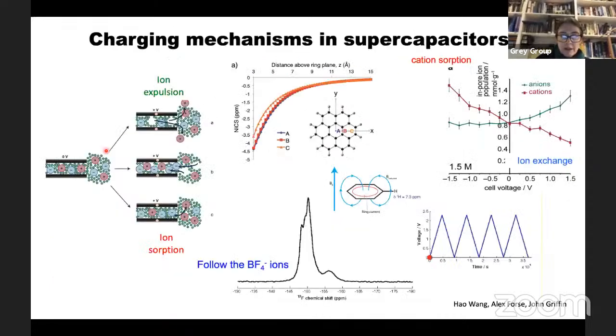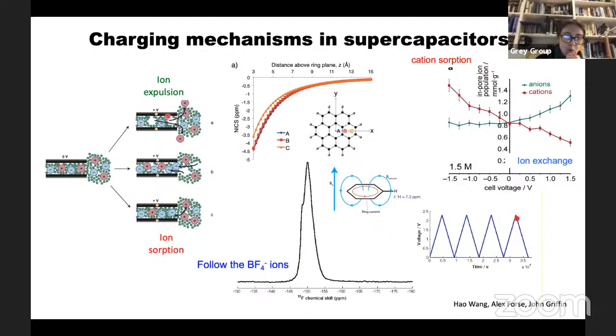And surprisingly enough, when we started in this field, people hadn't worked out how these compounds actually worked. These activated carbons consist of sheets of carbon. They're very graphitic. And if you do a thought experiment and you say to yourself, at 0 volts, I'm going to charge it positively. How do I store charge? Now, I said it was in a double layer, but it's a bit more complicated, it's really to do with how ions go in and out of the pores. And so you can imagine that if you have a positive surface, you could store charge by kicking out positive ions, or you could store charge by bringing in negative charge for charge compensation, or you could simply swap and do ion sorption. And so what we did over the years was to develop this whole metrology to answer the question of how these things charge.